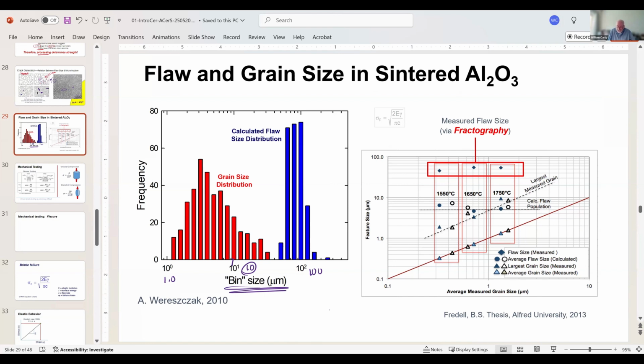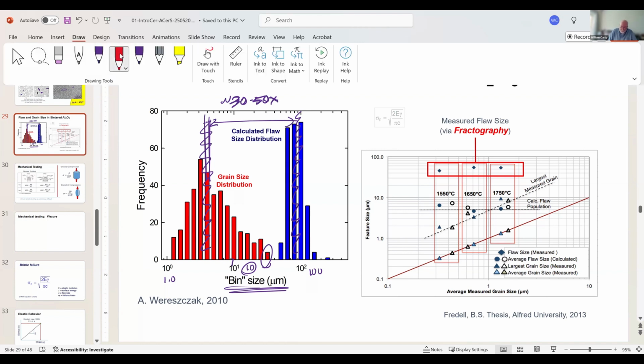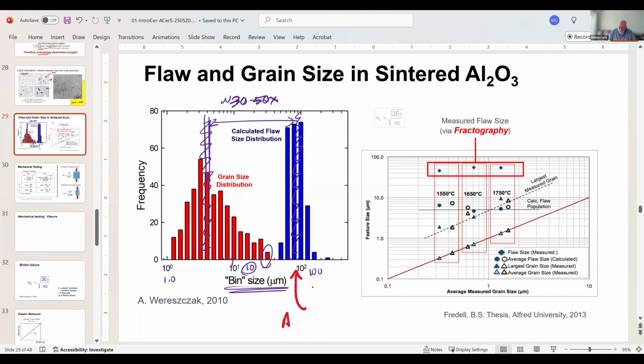And what I'm showing you is that the argument was that the largest grain in the system, which in one system might be this, which is a very few grains, dictates the strength, but he finds that's not true. And if I take the average of strength, which I'll say is here in the middle, and I look at the average over here, my difference is about a factor of 30 to 50x. That's a huge difference. It says that the flaws in the system are caused by agglomerates.